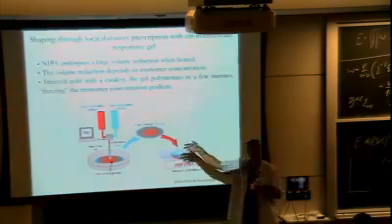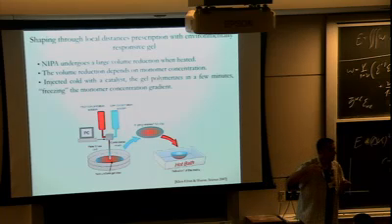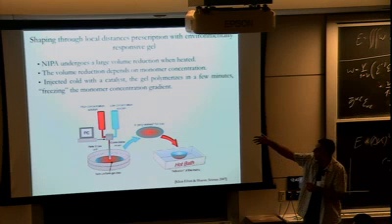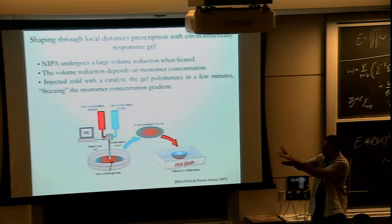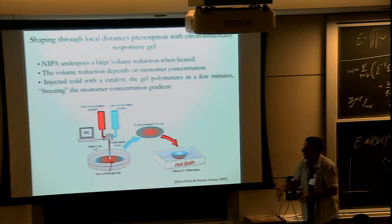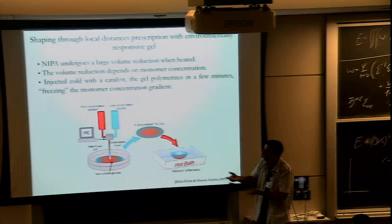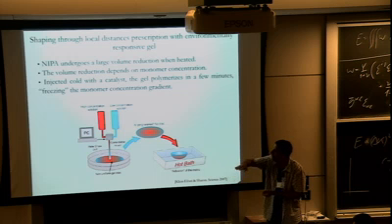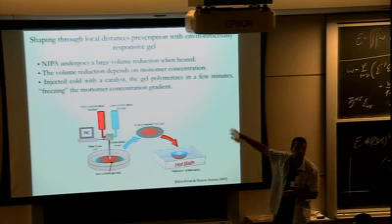How do you do this thing in a more controllable fashion? You can take something which is a hydrogel which is environmentally active. I have a gel in a high concentration and a low concentration, and I generate some mixture of that gel, and I let it cross-link in a cell such that all layers have identical structures.